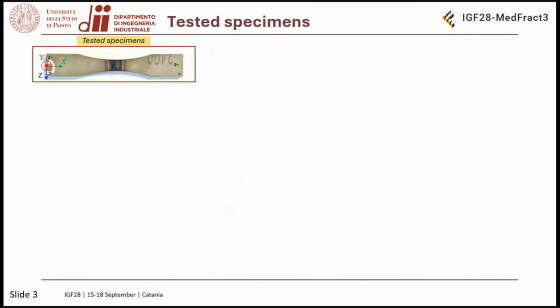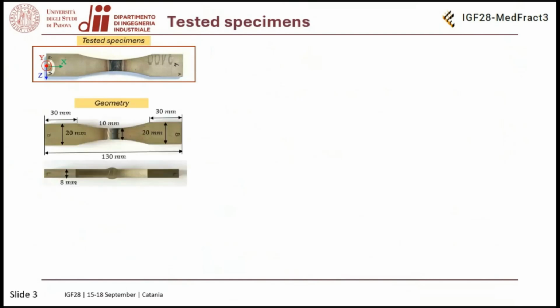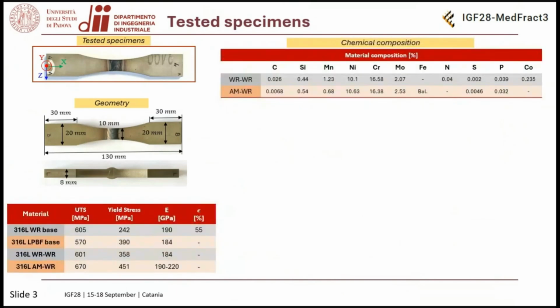Now that I briefly introduced you to the topic, I move to the main topic of my presentation, which is the experimental characterization both of traditionally manufactured welded joints and joints with an AM part. We test butt welded joints with a thickness of 8 millimeters. We acquire from the datasheet the chemical composition of our joints, and we also carried out some static tests in order to acquire the mechanical properties of our joints.